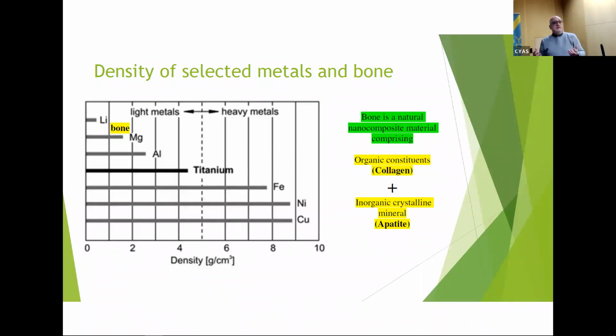In a quick comparison, why magnesium and bone and others? Just the density. If we choose the density as the parameter to make a comparison, bone and magnesium have almost the same density. The other heavy metals, titanium, iron, nickel, and even copper, are all heavy. That means if we insert an implant in the body, there is a kind of mismatch between bone and the implant, and it later makes implant failure because there is no match between the two.